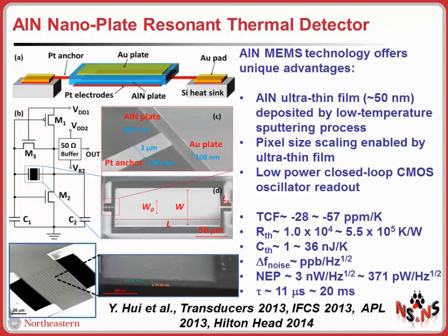So in our group, instead, we have been focusing on thin film aluminum nitride-based piezoelectric resonators. We did that because we believe aluminum nitride thin film resonators have some unique advantages compared to other piezoelectric materials. One key thing here is that ultra-thin aluminum nitride film, as thin as 50 nanometers, can be deposited by a low temperature sputtering process on any substrate. In fact, we demonstrated resonators that are as thin as 50 nanometers. So that's quite promising and important for this kind of thermal detectors.